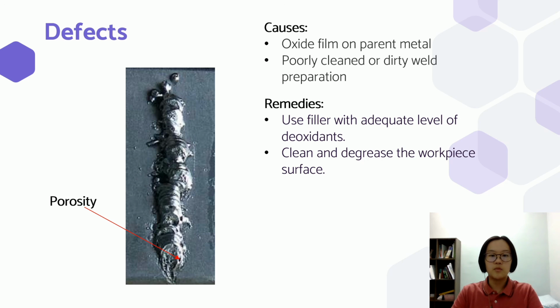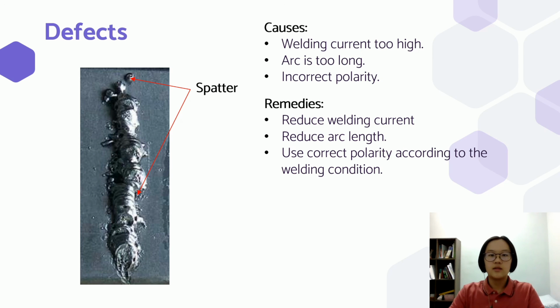The second defect is porosity, which can be caused by oxide film on parent metal and poorly clean or dirty weld preparation. To solve this, use filler with adequate level of deoxidants and make sure to clean and degrease the workpiece surface. The third defect is spatter, which can be caused by welding current is too high, arc is too long, or incorrect polarity. To overcome this, reduce welding current, reduce arc length, use correct polarity according to the welding condition.